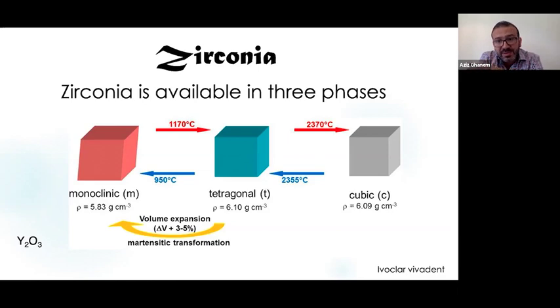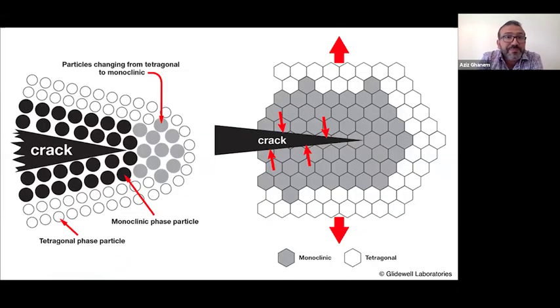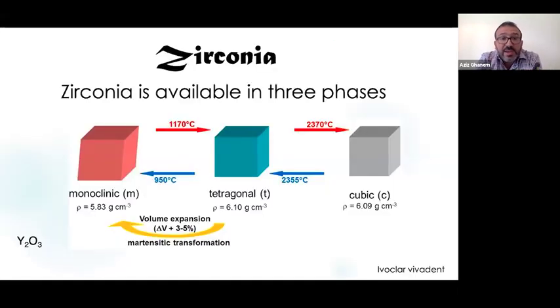the grain size. Okay, the less yttrium, the smaller the grain size, which is the crystalline tetragonal phase, and the more yttrium you add, the more you get the cubic phase, with a larger grain size. I will tell you why I mention the grain size, because it's really related to what I'm going to talk about later on. Right, okay. As I mentioned, the amount of the dopant really determines the phase of the zirconia.